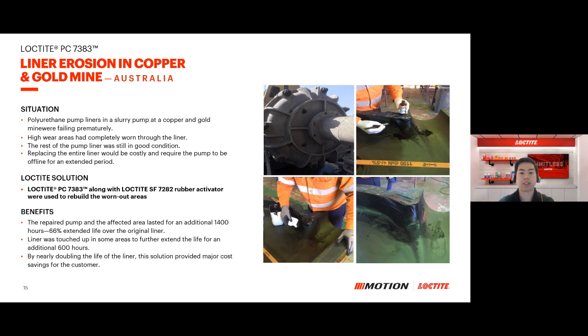Our first success story is from a copper and gold mine in Queensland. They were initially experiencing premature failure on their slurry pump PU liner, polyurethane liner, on their tailing side. When inspected initially, the high wear areas had almost completely worn through the liners, but the rest of the pump liner was still in very good condition. Now, to replace the whole liner would take a considerable amount of time and labor, and is also not very cost effective for the end customer.